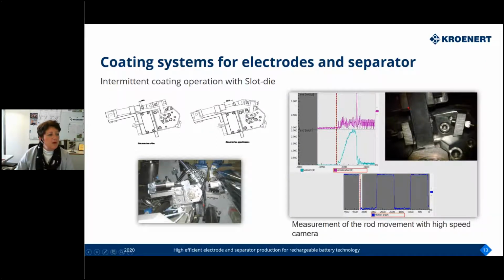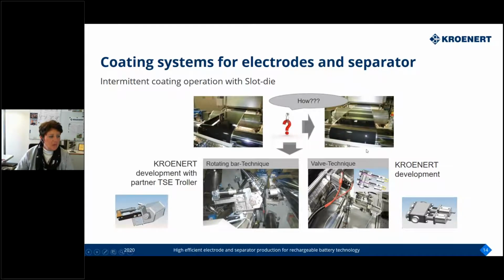Due to that, we developed a system where we have an oscillating rod inside the center of the die. This rod has a slit in the middle, and depending on the position of the slit, the slurry goes directly out of the die, which you see here, or it goes into a bypass and then back into the container. And with that, we can very precisely do such a start and stop operation, which you see here in the diagram, which is required for high performance batteries.